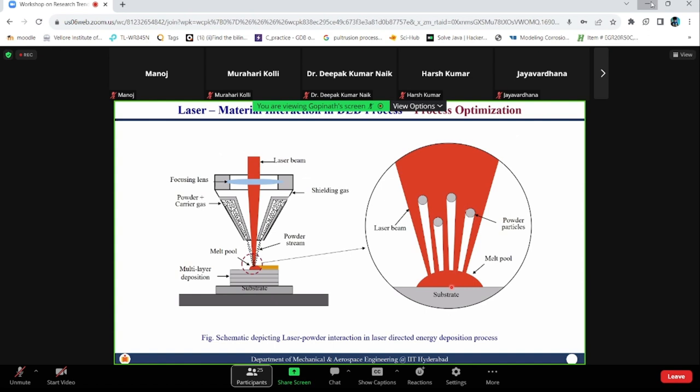See, if you look at this one particular pulse, let me see if I can zoom in. If you look at this one particular pulse, this is what we call the heating cycle. And once the laser moves from the point of interest, it will start cooling down. This is the cooling cycle. So heating and cooling, you can see it is narrow. But when it comes to here, you can see the cooling is slow. Slowly reduced, yes, because heat is getting accumulated. Then what we did, we changed the velocity. The moment you change the velocity, energy input per unit length changes and again it becomes smaller. Because energy reduced, it became very fast cooling. So essentially, this is one way to control the heat accumulation effect.